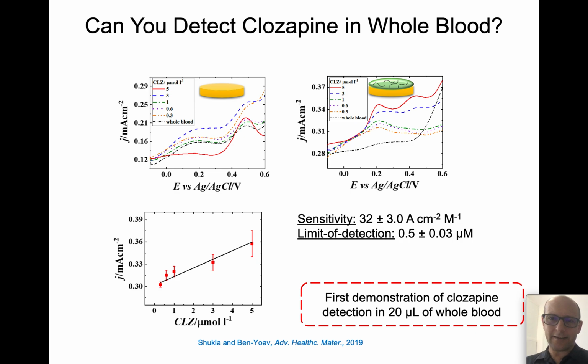And we achieved a very good limit of detection of 0.5 micromolar, and that's very relevant to the clinical threshold, when psychiatrists told us they would like to know if the levels of the clozapine in the whole blood are higher than 1. So we actually got a 2 times better limit of detection than the clinical threshold. And this is the first demonstration of clozapine detection directly in microliter volume samples of whole blood in the required clinical range. You can read more about it in the Advanced Healthcare Materials paper that we recently published.